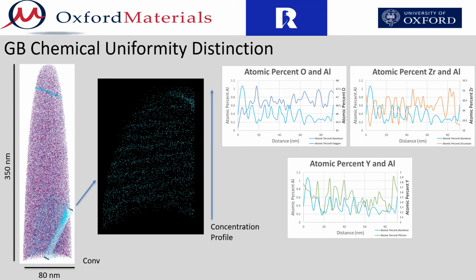Some grain boundaries also demonstrate structuring within the plane of the boundary. The grain boundary shown in this slide, from a conventionally sintered specimen, shows ordered regions of oscillating high and low concentration of aluminium. An ROI was extracted around the width of the boundary and rotated head-on to view the evident structuring. The concentration profiles on the right side of the slide demonstrate that while oxygen concentration shows little correlation with the aluminium concentration, zirconium depletion and yttrium enrichment correlates with the aluminium enrichment.